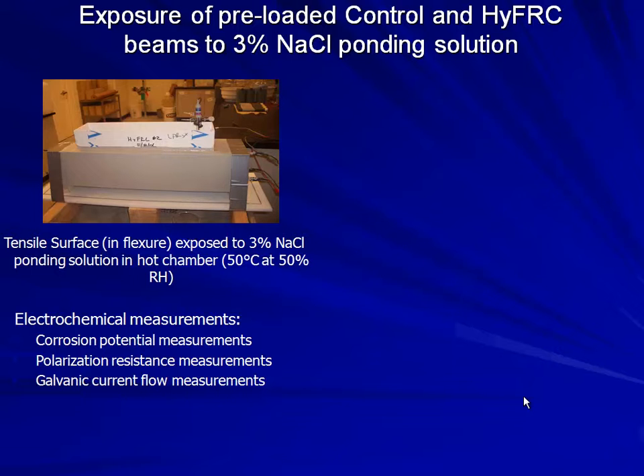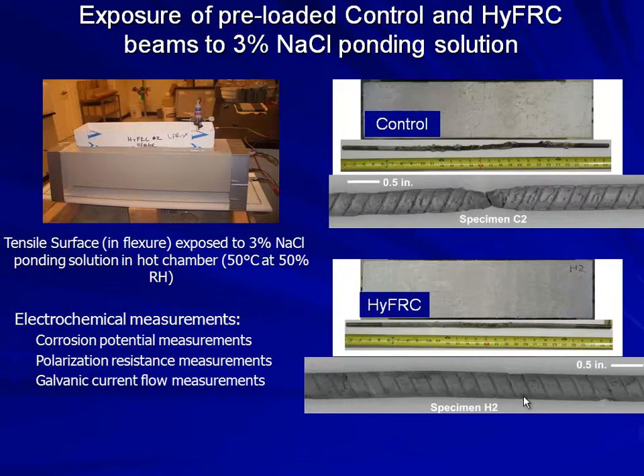But what is very visual, of course, is when you look at the rebars. If you look at the rebars right here, this is your control specimen, and this is the dominant crack that you see. You have corrosion along the whole rebar. We retested the specimen, and when you retest it, the slab fractured at a much lower strain level. So you had premature failure of that slab. Whereas with the hybrid fiber reinforced, you have almost no corrosion damage on the rebar.